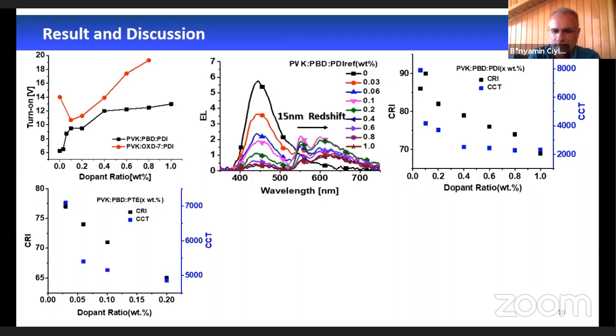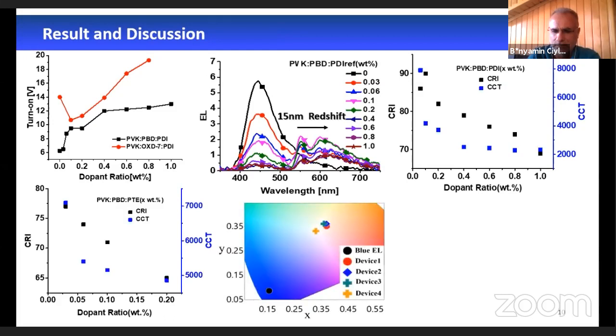In order to increase the visible region coverage and enhance the white light properties, PDI and PTE were used together in the active layer, separately optimized. PDI ratio is stable in devices 1, 2, 3, but PTE ratio is increasing. However, as can be seen, it doesn't cause a large shift in CIE coordinates. However, when the PDI ratio is decreased, the CIE coordinate shift occurs.